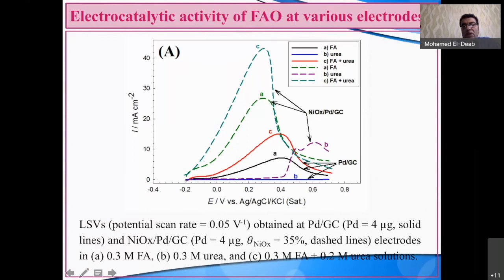So urea oxidation is not taking place at this potential domain, but the addition of urea to formic acid enhanced formic acid oxidation too much, as you can see. Here also, on palladium modified with nickel oxide, you can see much more increase in the oxidation current of formic acid in presence of urea as well. So what is the role of urea here?